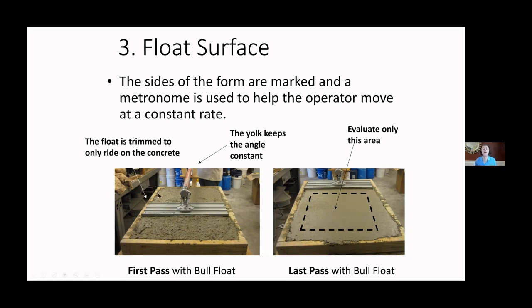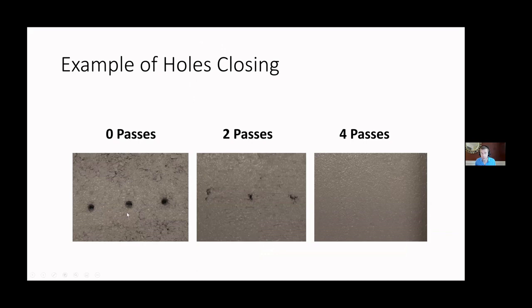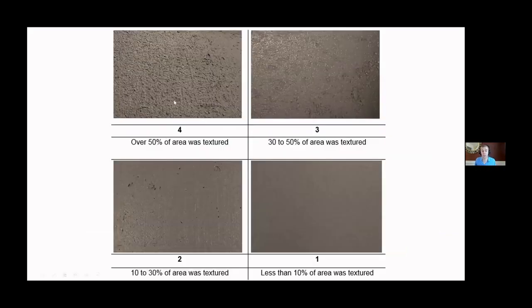What am I talking about? Closing the holes. So here's some holes at the beginning. This took about 4 passes. Between 4 to 6 passes is a really, really good performing system or mixture. Here is the surface texture. There is poor surface texture. There is the best surface texture. We don't need the best for our concrete. We can live with 10 to 30% overall surface voids, and that's what we're shooting for. That's what we want. And we want to know how many passes does it take to get there.